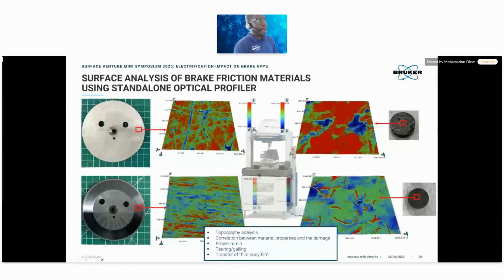Characterization of the material before testing, and even on the disk and the pad itself, and after, with the formation of different areas, where we see some areas with polishing surfaces, some torn material around, and even on the disk area, which is probably cast iron, where we have a transfer layer coming from the brake pad. If we go to more analysis, we need to do chemical analysis to see better which type of structure we transfer on the surface, which type of third layers we have formed, and what is the impact on the roughness of the surface after this running-in.